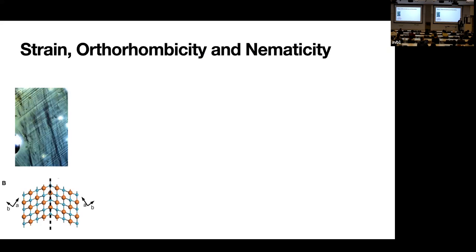Here's another example of a kind of susceptibility and transition that you might look at. Here I've got a cartoon of a crystal that is what we call orthorhombic. What that means is that the actual repeating cells in this periodic system are little rectangles. And they form domain boundaries because the rectangles can be in two different directions. This is an optical image of what those domain boundaries look like. They form these straight lines, and this is basically the domain walls of rectangles pointing in one direction versus in another.